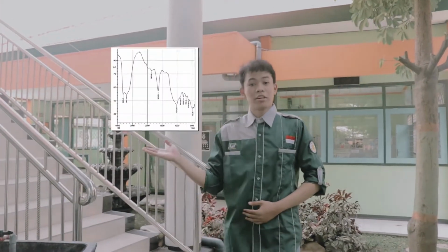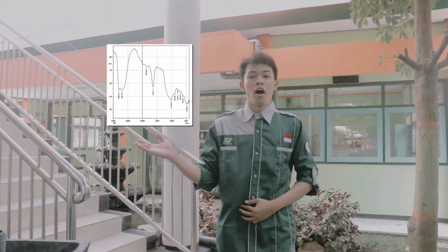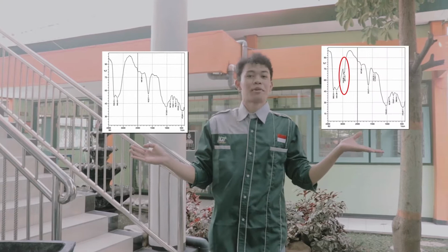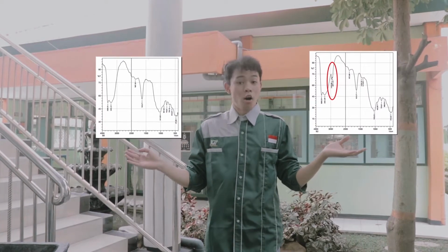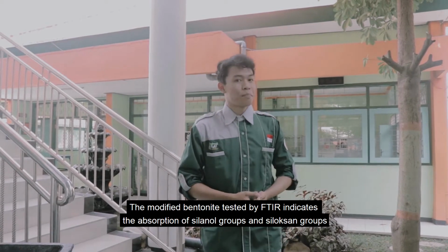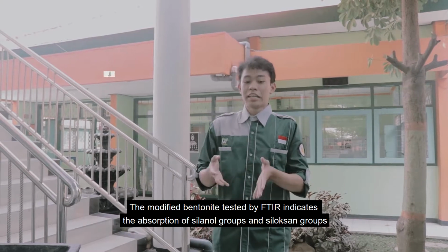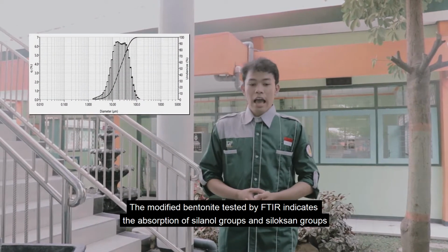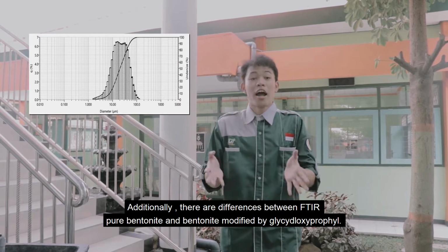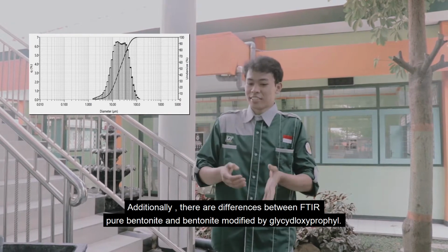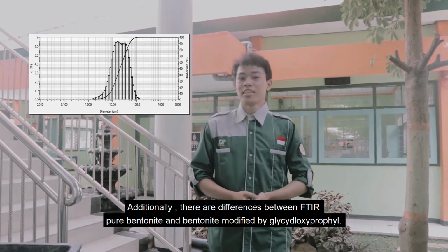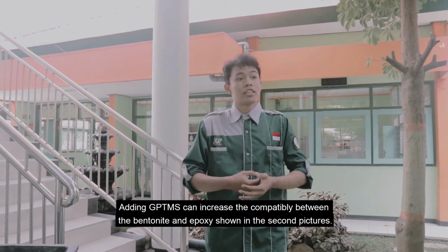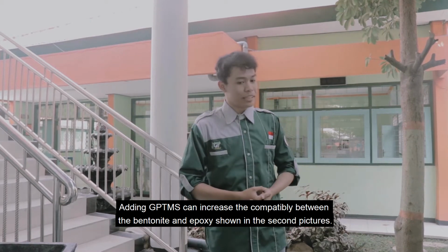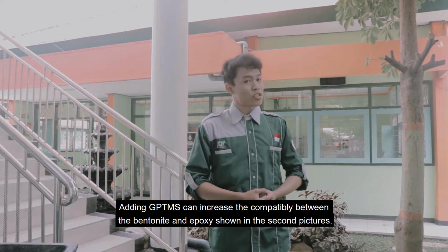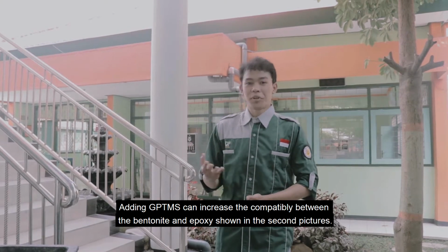Alright, this is the result of the infrared spectrophotometer of pure bentonite, and this is the result of the infrared spectrophotometer of bentonite modified by glycidoxypropyl trimethoxysilane. The modified bentonite tested by FTIR indicates the absorption of silanol groups and siloxane groups. Additionally, there are differences between FTIR of pure bentonite and bentonite modified by GPTMS. Adding GPTMS can increase the compatibility between the bentonite and epoxy, as shown in the second picture.